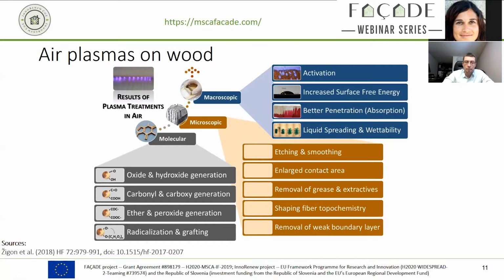So there's a lot of things that can be generated by the plasma, and a lot of reactions that can take place, but also at the same time they will take place. And it's hard to really specify one reaction that you want to have as the main part of the treatment. That's hard to really constrict. So you're typically getting, for example, for air plasmas on wood and on many polymer materials, oxides, hydroxides, carboxy groups, even ether and peroxide groups, and this can then also help to create radicals or to induce grafting. Also, depolymerization can be a topic, an issue, or a benefit on different polymeric materials.